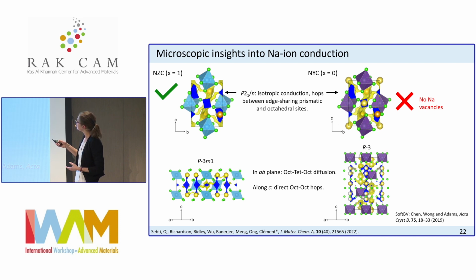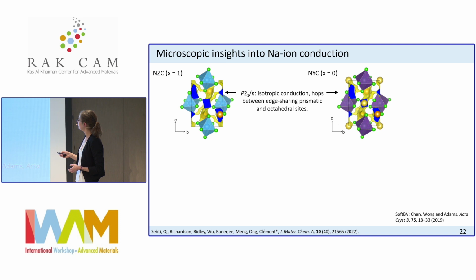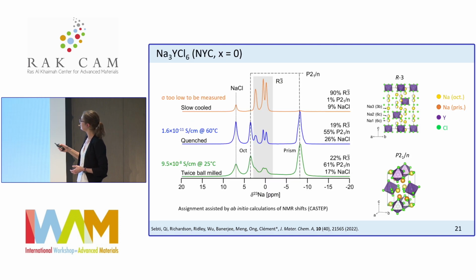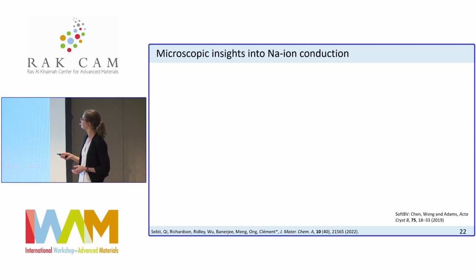For the NYC structure, we believe that this is the polymorph that's not able to conduct because this one has no sodium vacancies. And the increase that you see upon ball milling, sorry, going back to this here, the increase that you see in conductivity is likely due to disorder in this R bar 3 phase, as we observe from the broadening of the resonances that are attributed to this R bar 3 phase.